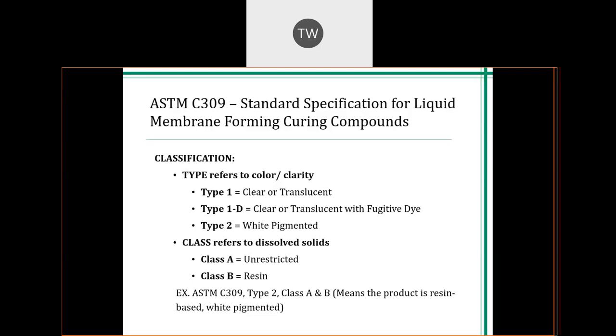Another rule of thumb with type 2 is that it needs sufficient wear and outdoor exposure to actually dissipate. If you were to use this at an indoor warehouse with minimal traffic, the pigment may stay on your surface and not be broken down and dissipate in a desirable period of time, or it's going to leave you an opportunity to add other treatments and coverings to your surface.